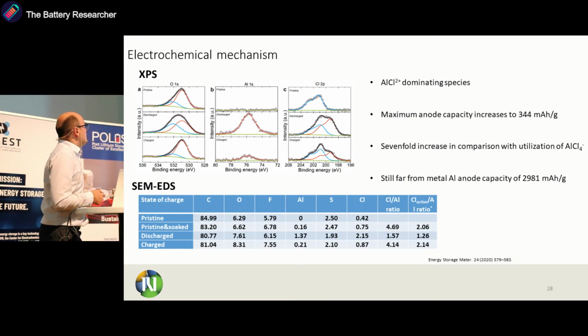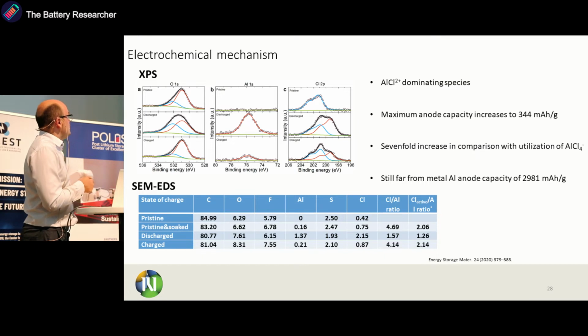And we did it first with XPS. So basically we saw here in oxygen that we have a decrease of this carbonyl peak during discharge and going back. But during the discharge, we have increase of aluminum species and also chloride species. This initial chloride species is from the monomer unit, which was synthesized from chloride, but then we have additional chloride coming in. So this means that we still have some chloroaluminate species there, although this contribution then decreases in discharge.